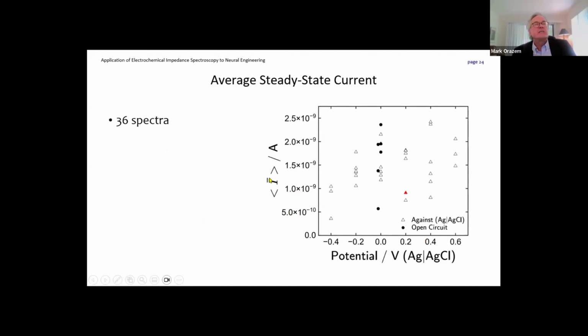Other thing I want to mention is that when we look at the steady state current as a function of applied potential, and the dark circles are open circuit, we see that the current effectively is open circuit the whole time. This represents zero current. So what that's telling us is that we stayed well within the water window. We are not evolving hydrogen, we're not evolving oxygen, and there is the iridium oxidation and reduction, which is a redox reaction that takes place in this system.